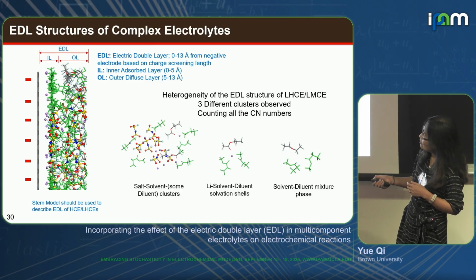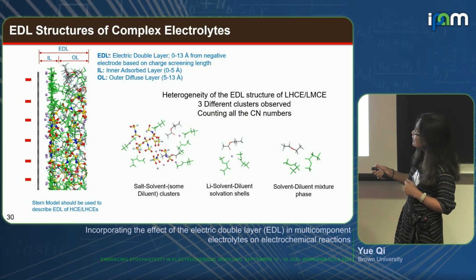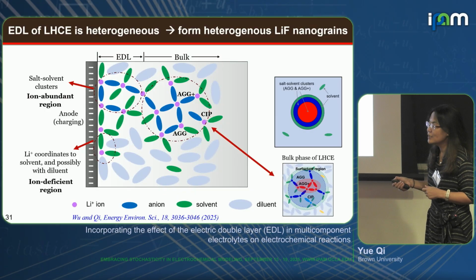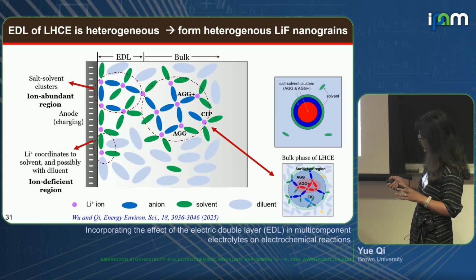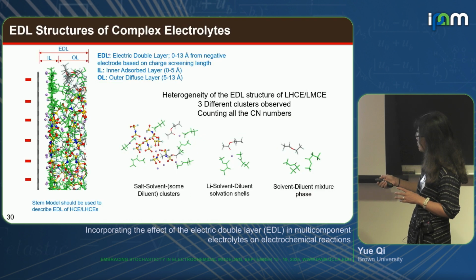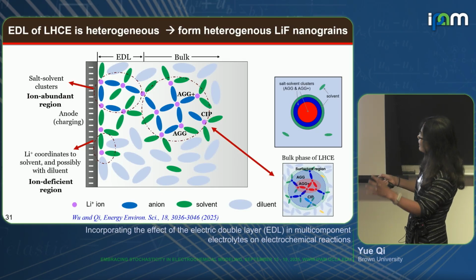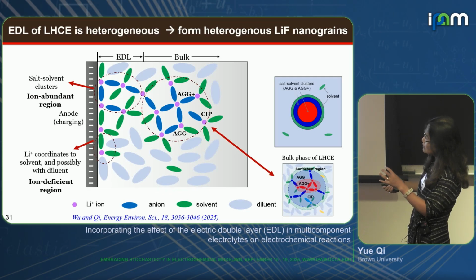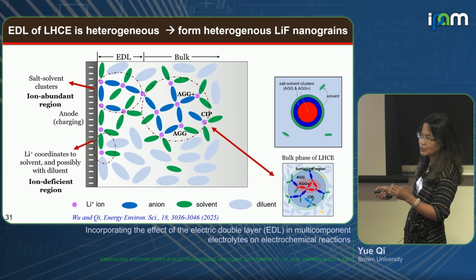So we then want to understand, if you have this heterogeneous structure in your liquid, what happens on the negative surface, right? So we do our MD simulation and look at all these clusters. This is not an imagined schematic; it is a schematic based on our counting. We counted all the coordination numbers, and we see how in the bulk we have these aggregates and solvent clusters, and a diluent where the solvent has a percentage dissolved too. Then near the interface we still have these salt aggregate clusters, and then we start to see a percentage of ion and diluent half-solvation structures. Right?